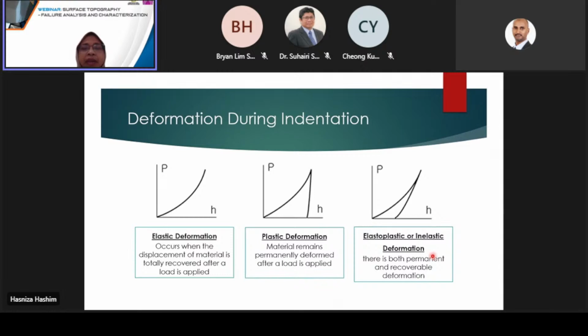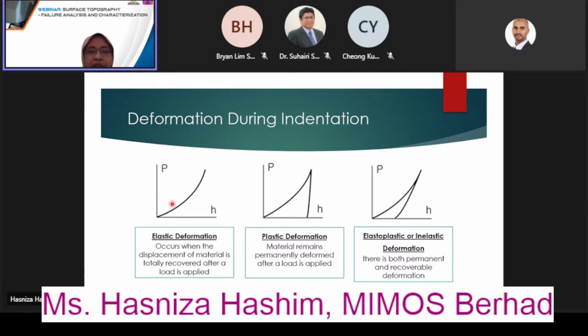So when we talk about indentation, we also need to at least have some information about deformation during the indentation. For the first one, elastic deformation occurs when the displacement of material is totally recovered after force is applied, meaning that the loading curve and the unloading curve would essentially perfectly overlap, like here. If the material remains permanently deformed after a load is applied, it's called plastic deformation, meaning you would have a loading phase and then a straight down drop for the unloading phase. In nano indentation, we are hoping to see something in the middle of the two, called either elastoplastic or inelastic deformation.